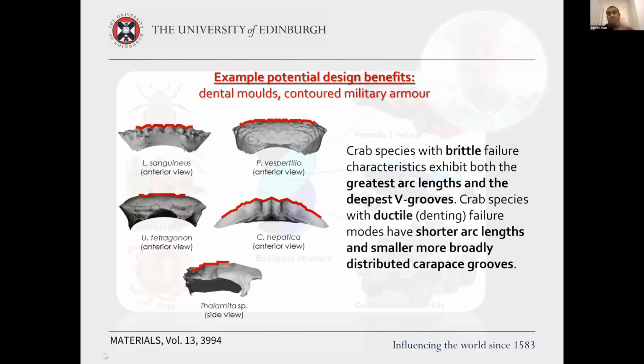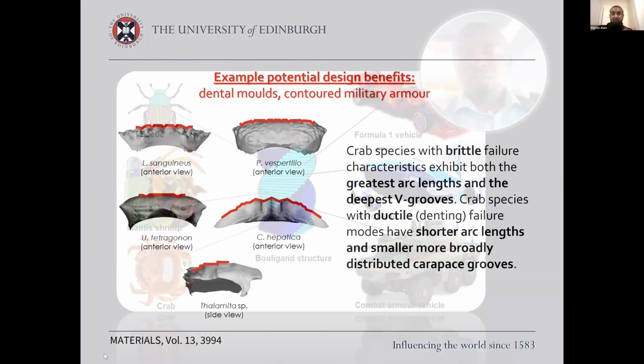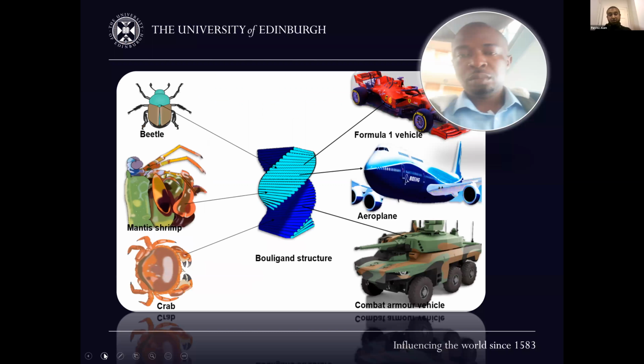Now, that's the geometry that relates to the outside of the crab. When it comes to the inside of the crab, there are also impact-resistant geometries. And basically, inside the crab shell, and this is true also for the mantis shrimp dactyl club, and also for the beetle shells, you have Bouligand-structured composites. These are fibrous, laminated structures that basically twist like a twisted plywood structure over and over again. For each subsequent laminate, it twists at a slightly different angle from the previous one. And basically, if you were to smash a structure like that, then the fracture path would have a much more tortuous journey to make than if it was a unidirectional composite where that fracture line could just work its way straight down.